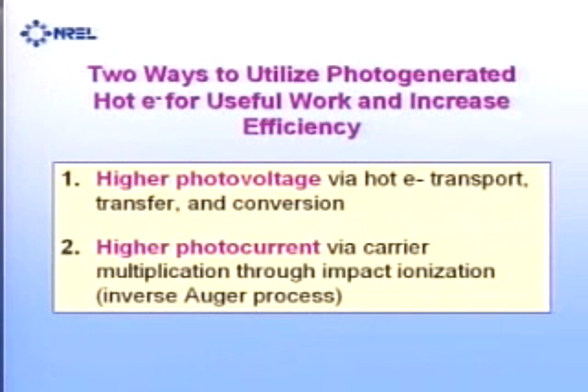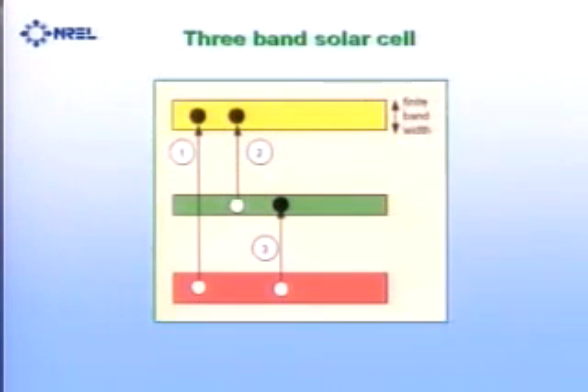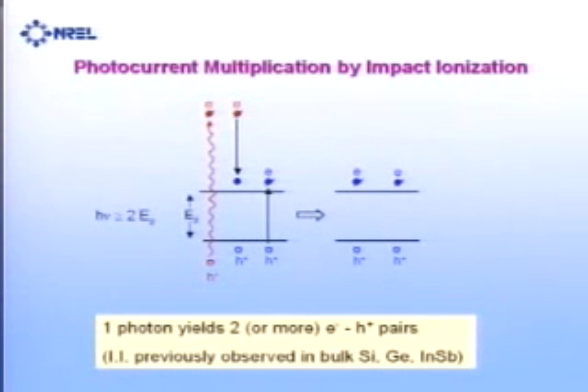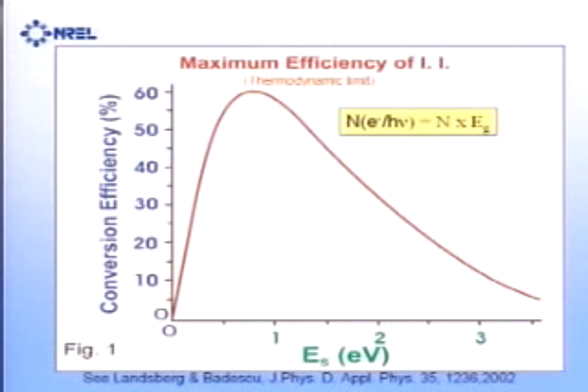But recently, we realized that you could generate additional carriers if the photon energy was sufficiently high. And this, in bulk materials, is known. It's called impact ionization. It's been observed previously in silicon and germanium and other semiconductors. And the thermodynamics has been looked at by many people, most recently by Landsberg about 3 years ago. And the efficiency, as you would expect, is close to what we calculate for conversion of hot electrons in general.